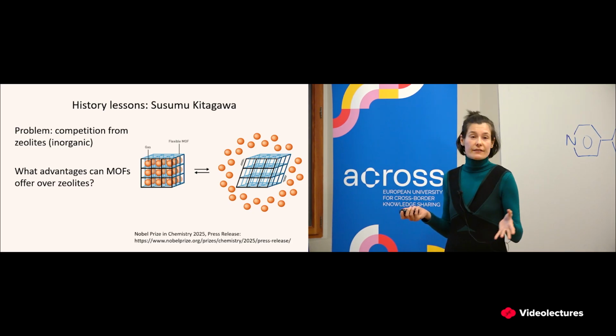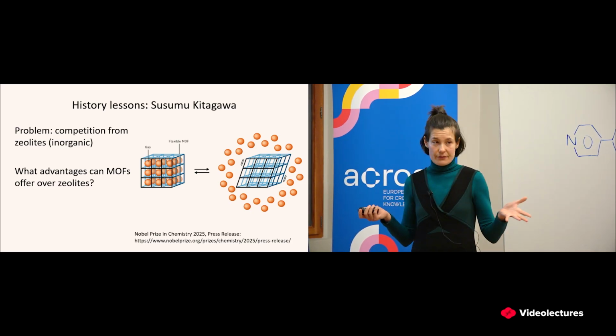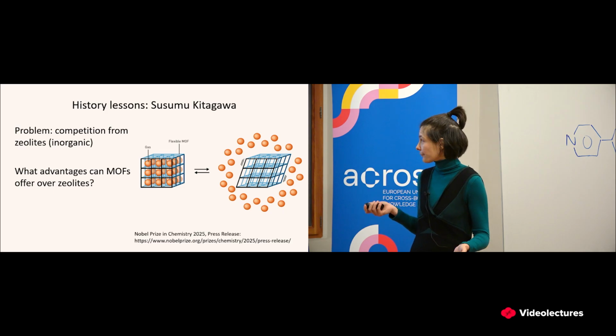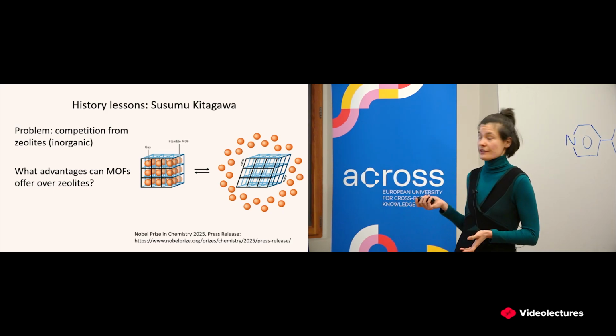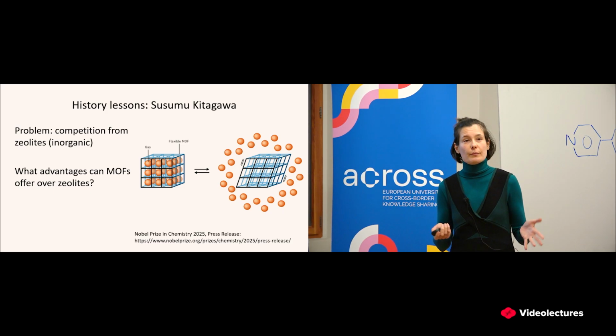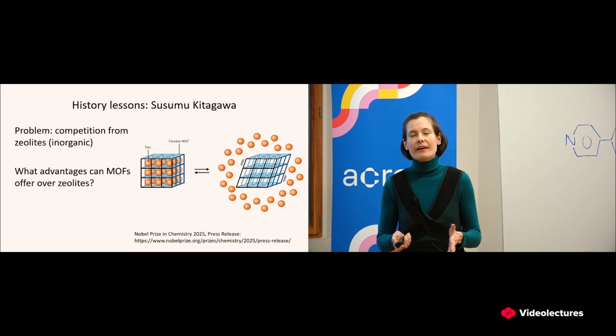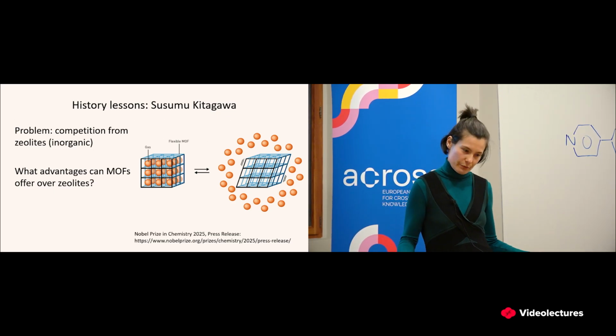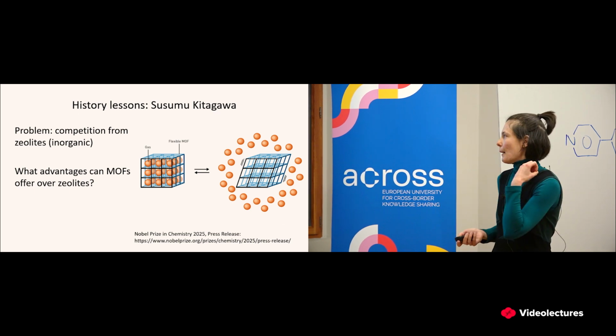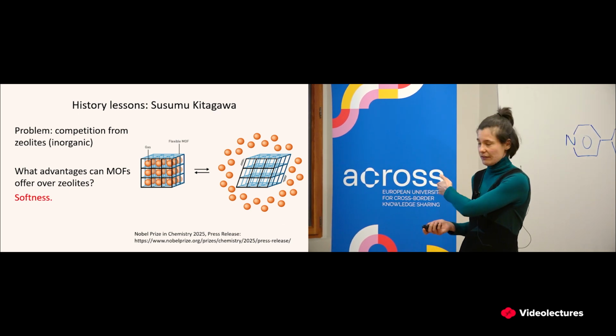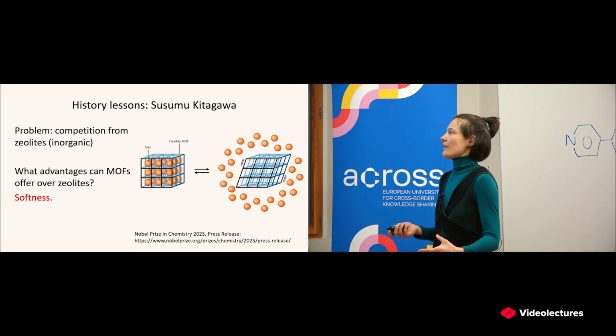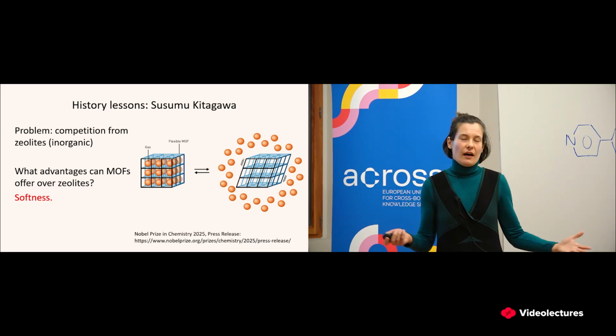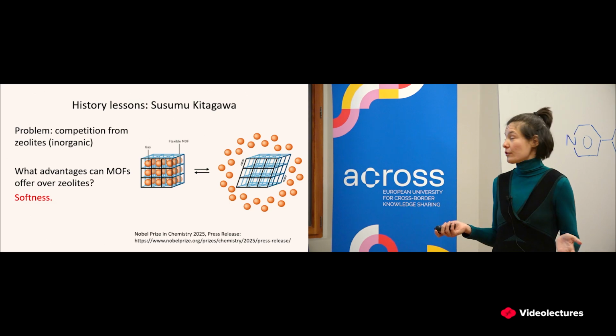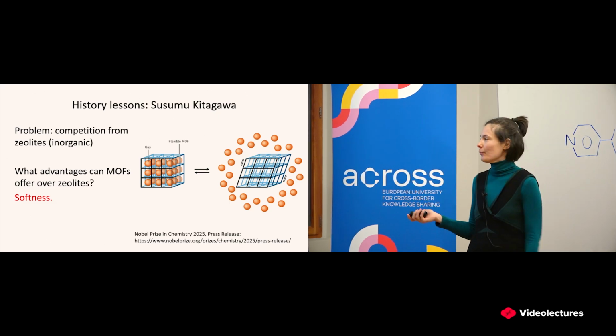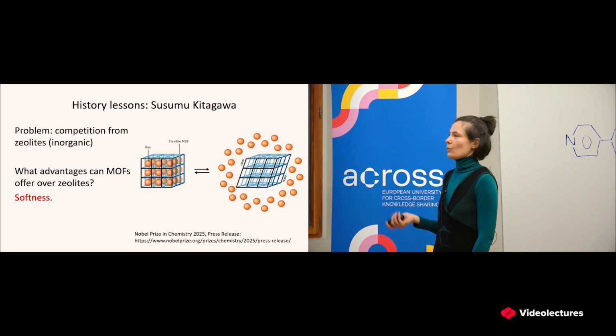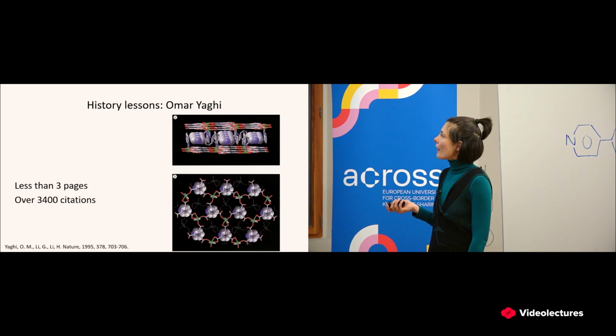And what you can see is that when you release these gas molecules, when you remove them from the pores, the structure of the MOF actually changes slightly, right? So this shows that the materials are flexible to some extent, and this is something that zeolites cannot do, right? Zeolites are hard materials, and they cannot exhibit this kind of behavior. So softness was one of the advantages that at that time was explained as the reason for which MOFs are superior or different, but still useful, even though people used and worked with zeolites.